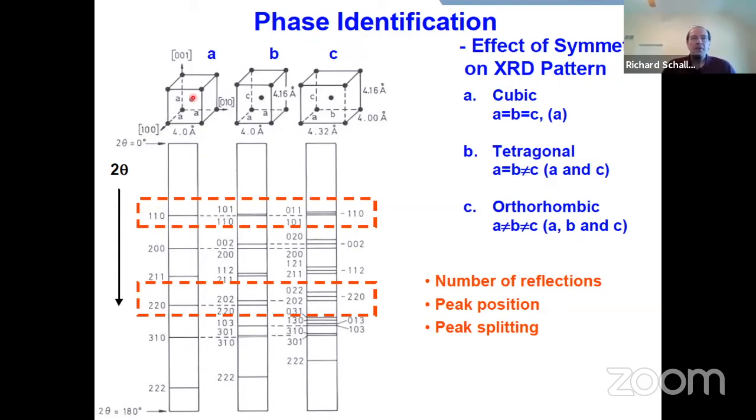And just a little bit about that is that if you have something like, say, a perfect cubic unit cell here, there are fewer distances that are involved in that perfect cube because you have all these different lengths being identical. So when you measure diffraction, there are different planes in this real space image, but in Q space, they have the exact same separation, and so all lead to the exact same reflected angle. So you see fewer peaks for a cubic cell.